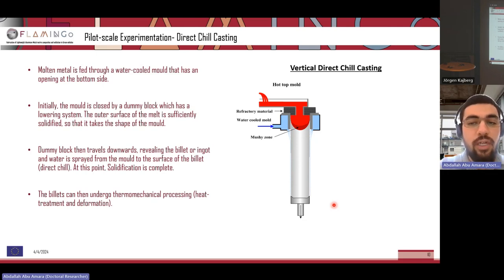The idea is, direct chill casting is a method that begins with melt being poured through a water-cooled mold, as you can see here. So this is the aluminium melt in red. The melt travels down through this water-cooled mold, and then it goes to this dummy block. The dummy block begins at the top, and as the melt begins to solidify, the dummy block begins to move downwards. As the dummy block moves downwards, water is sprayed on the billet, and so it solidifies very quickly and the cooling rate is very fast. So what we get forming is a high strength billet with a fine microstructure.